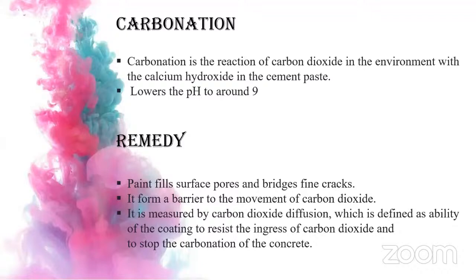Carbonation of concrete is a process by which carbon dioxide from the air penetrates into concrete through pores and reacts with calcium hydroxide to form calcium carbonate. It has been seen that conversion of calcium hydroxide to calcium carbonate by the action of CO2 results in a small shrinkage. In the presence of moisture, CO2 changes into dilute carbonic acid, which attacks the concrete and also reduces the alkalinity of concrete. In actual practice, CO2 present in the atmosphere in smaller or greater concentration penetrates into concrete, carbonates the concrete and reduces the alkalinity of concrete.